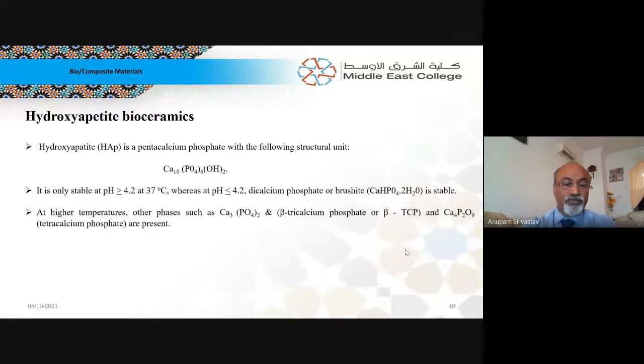So it is stable between the pH values greater than 4.2 at temperatures 37 degrees C. At lower than 4.2, it dissolves or disintegrates into dicalcium phosphate, or what is called brushite, which is also stable, but this transition is not acceptable to the body in general. So we prefer not to use it as such. That is why we do some changes.